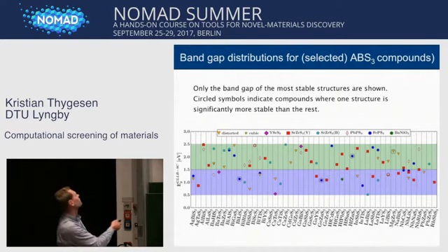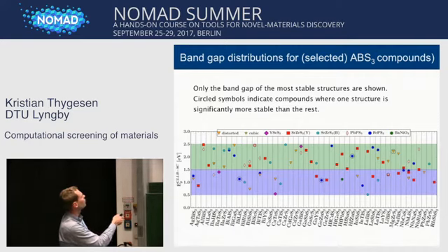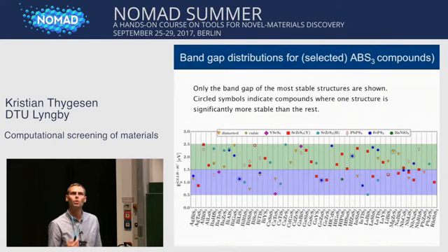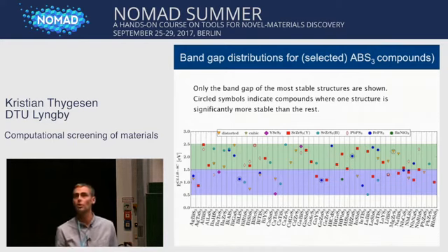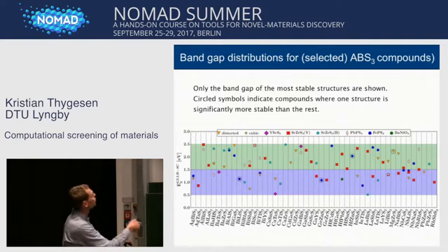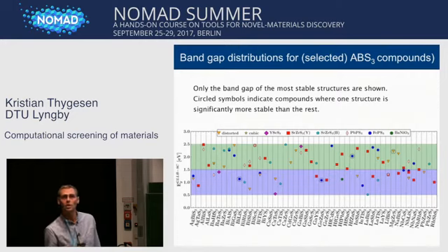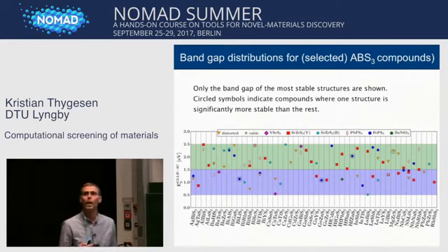So for example, here is silver tantalum sulfide. You can see there is only one material here. In this structure up here, you can see that has a band gap of 0.7. So that's something that could be interesting for photovoltaics with a single semiconductor absorber, so we keep that. So the blue window down here are materials that would be interesting for single crystal photovoltaics, and the green up here is large band gap materials for tandem cells, okay, which is our main interest.